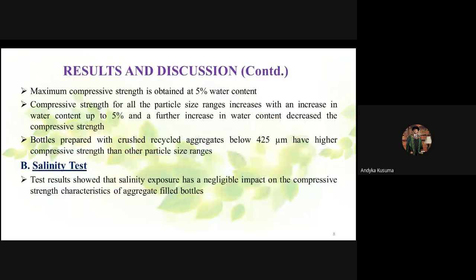After that, the salinity test was conducted. For the salinity test, we took 350 gram of sodium chloride and mixed it with 10 liters of water. The specimen with 5% water content, which showed the maximum compressive strength, was selected for the salinity test and submerged in the saline solution for around 28 days. Thereafter, the compressive strength was tested.